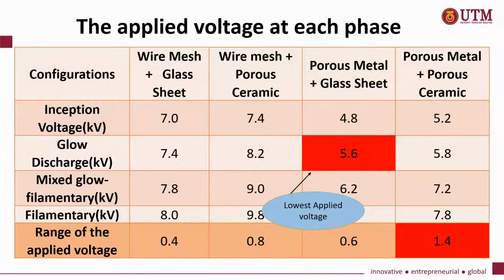Since the porous metal has the feature of gas penetrability, the oxygen gas that is fed into the gas chamber is able to diffuse through the porous layer. An extremely uniform distribution of the gas flow will then be allocated along the entire area of the porous metal, and therefore the plasma intensity was strengthened. For this reason, only a lower applied voltage is needed to initiate the glow discharge plasma.